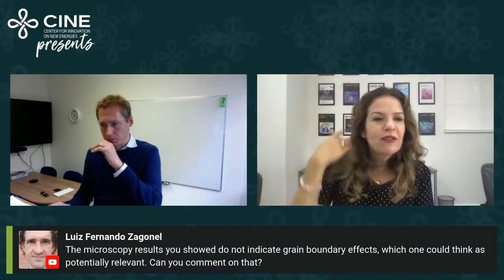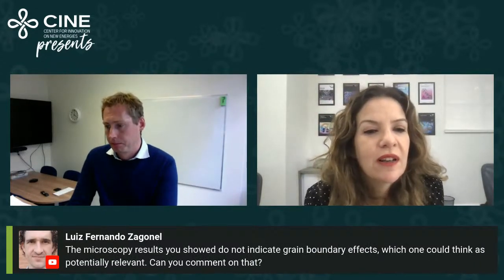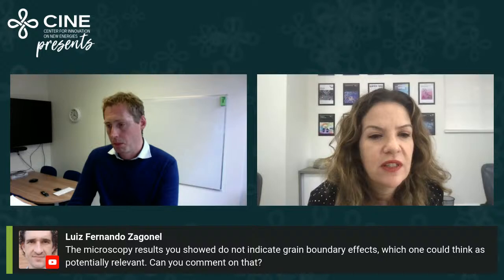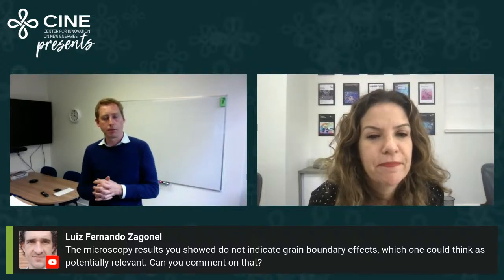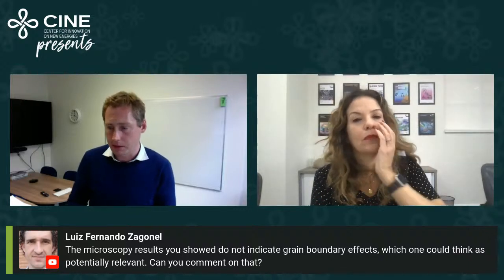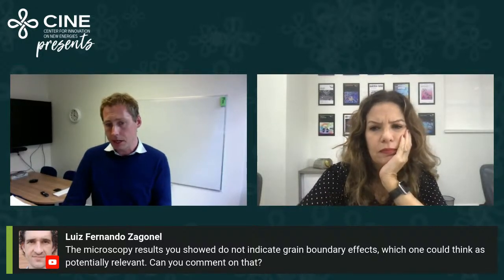Okay, I have a question from Professor Luis Fernando Zagonel. The microscopy results you show do not indicate grain boundary effects, which one could think as potentially relevant. Can you comment on that? Yeah, this is a good question again. So the grain boundaries are complicated in these perovskites, which maybe is not surprising, as they are in many systems, but it depends a lot on the composition. What we're seeing in these formamidinium-rich samples is that these hexagonal polytypes, some small impurity grains that are there, are the problematic grains. They do tend to sit at boundaries, actually.